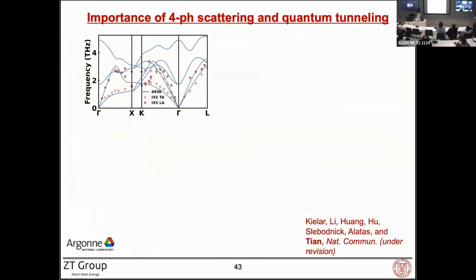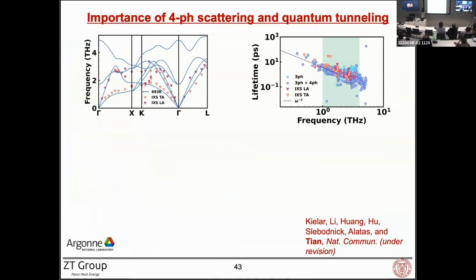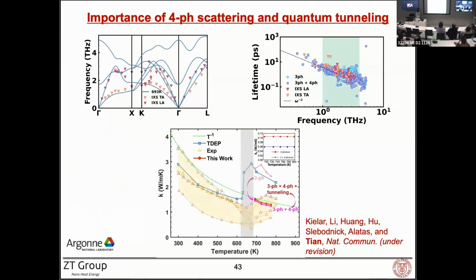So with that, let's first take a look at phonon dispersion. We measured those markers using inelastic X-ray scattering, and our calculation is in blue. So you can see this phonon dispersion agree pretty well. And then we look at the lifetime. So if we only consider three phonon scattering, it significantly overestimate the phonon lifetime compared to the measured lifetime, especially between this 1 and 4 terahertz range.